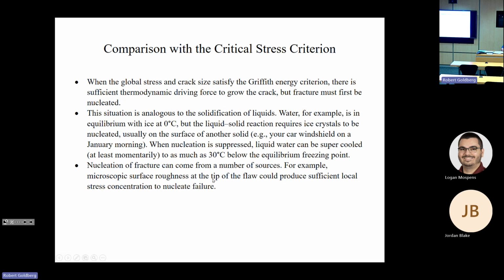So it's the same idea as fractures: even if you have all the other conditions, you need to have something to trigger the fracture. And usually things that trigger fracture have to do with local stress concentrations. In the real world, surfaces have roughness. So at the tip of your flaw, there's a microscopic surface roughness that can create sufficient local stress concentrations to start the failure process. You just have that extra little, very localized stress concentration, which is just enough to